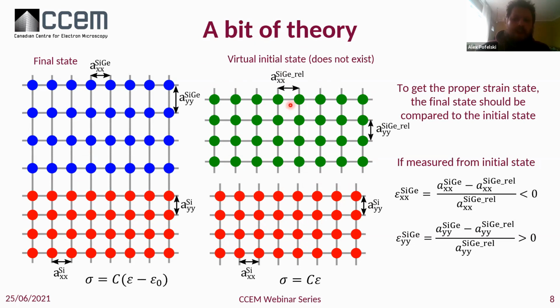We are not creating the silicon germanium layer independently and compressing it after. So even if we wanted to have this initial state, in that particular case, especially in molecular beam epitaxy, we don't have access to it. So sometimes it's not even an idea to bother with this initial state. We just keep everything at the final state and use internal references to do our strain measurement. And then to make the proper interpretation of the deformation,